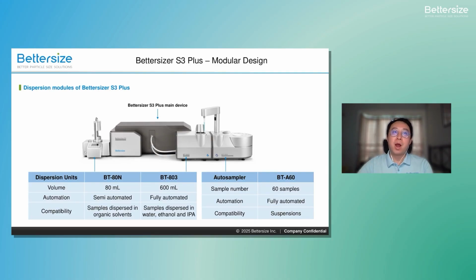To help better utilize the unique design of Bettersizer S3 Plus and to achieve the best performance, to do the measurements more easily, we provided two dispersion units and one optional auto sampler. If the particles are insoluble in water and come in large quantities, such as gypsum or raw limestone powders, then BT803 can be the ideal choice. It is a fully automated dispersion module with automated test functions. Also, it is compatible with ethanol and isopropanol alcohol, making it a good choice for semi-finished or finished cement products that may undergo particle size changes in water.